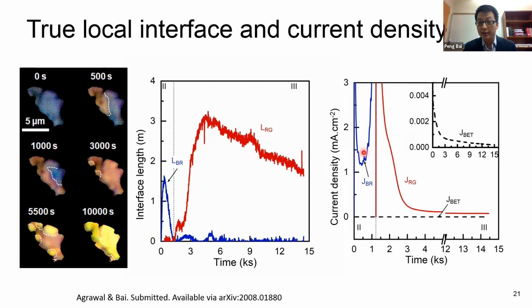So again, you can see here, this is roughly 1 milliamp per cm squared, compared to the geometrically averaged current, averaged over all the available surface area of the particle, which is almost 3 orders of magnitude lower, right? So you have to use this true local current density to characterize or to evaluate the electrochemical processes.